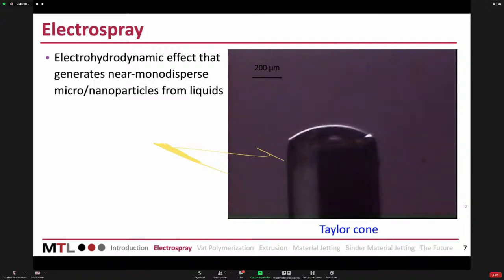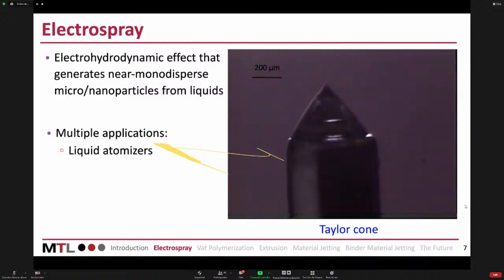So what you are not seeing is that I have a counter electrode on top of the capillary, and I'm biasing a voltage. And when the voltage is high enough, then the meniscus does this effect called a Taylor cone. And what we like about this phenomenon is that it produces particles very uniformly. And you can use it, for example, to atomize. Okay, you have an atomizer for liquids. You can also have a combustor. The combustor has an atomizer, and then you have a combustion chamber, so you efficiently extract heat from that combustion.